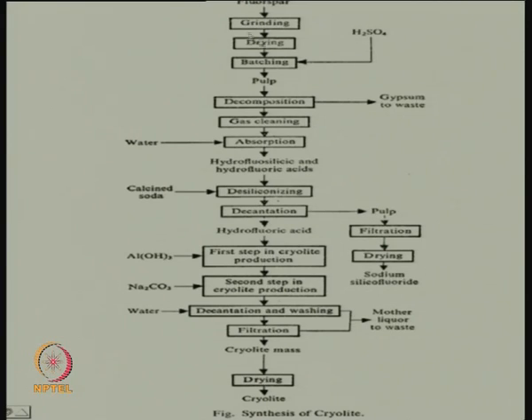We will start with fluorspar, which is calcium fluoride: grinding, drying, batching, pulp, sulfuric acid treatment, decomposition, gypsum to waste, gas cleaning, absorption, then hydrofluorosilicic acid and hydrofluoric acid treatment, desiliconization, decantation, hydrofluoric acid, and a whole lot of other steps. Finally, we will get cryolite. We will add sodium carbonate here somewhere to get the sodium part. The calcium fluoride part is coming from the top.